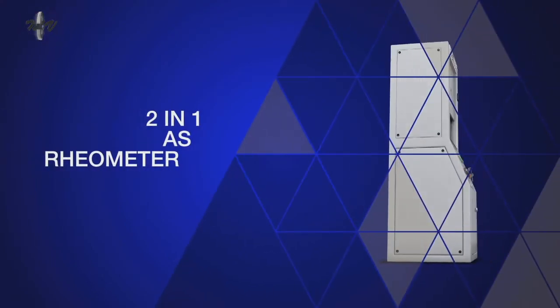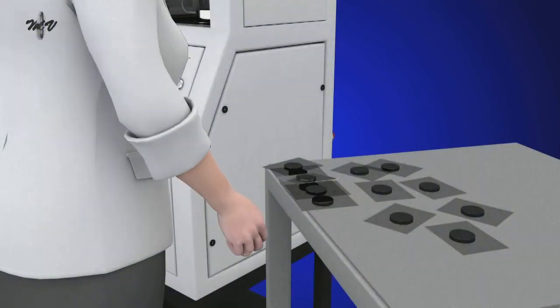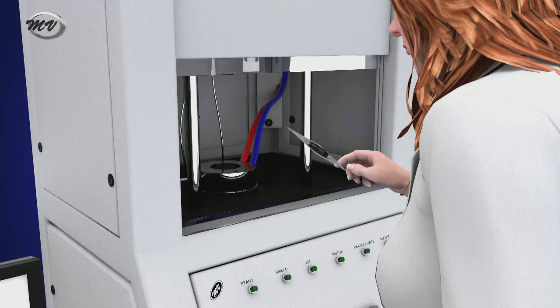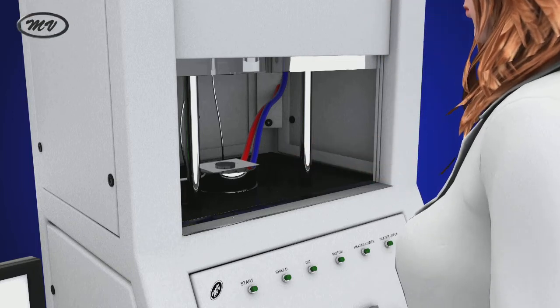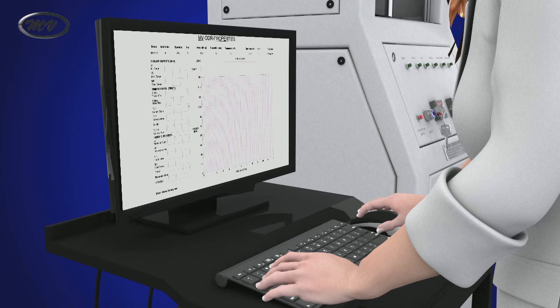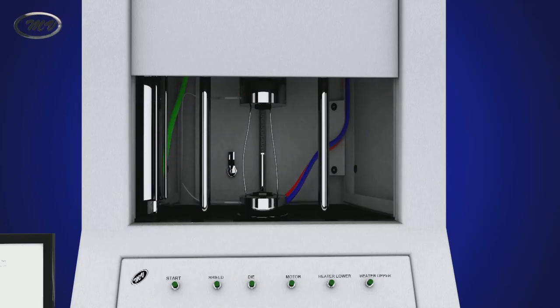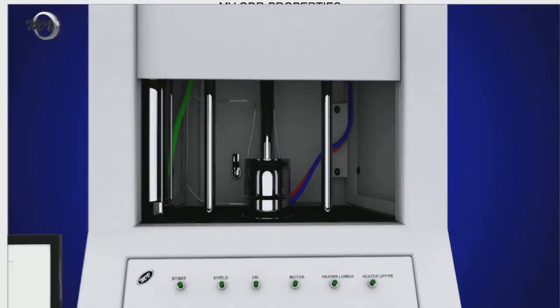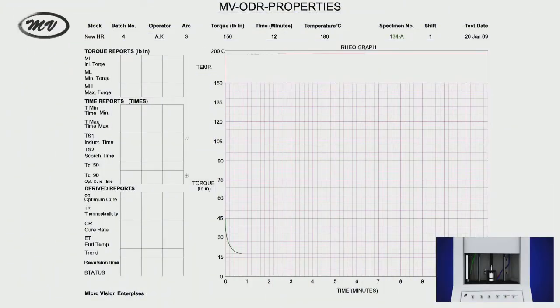To use the 2-in-1 machine as a rheometer: a small test piece of rubber compound is contained in a sealed test cavity under specified positive pressure and maintained at a specified constant temperature. The test piece is then enclosed with a rotor and is oscillated with a small specified rotary amplitude. A plot of this torque gives a typical graph called a cure curve or rheograph.